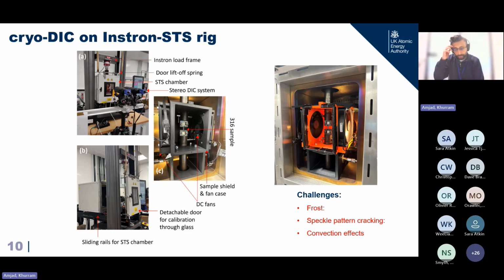And the other challenge with regards to DIC is that, for example, if you're testing a material like 316, which remains very ductile even in cryogenic temperature, we are talking about up to 50% gauge extension. So you start getting your speckle pattern starting to crack, and the speckle pattern acts as a strain witness. If it starts to debond, then your strain measurements are essentially useless. So we have to develop a technique where we can do a speckle pattern which can stretch up to 50-60% without cracking.